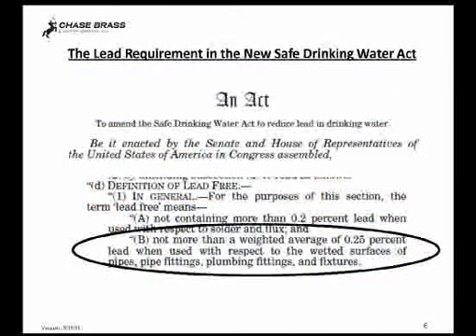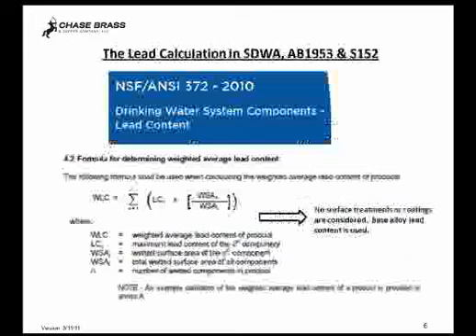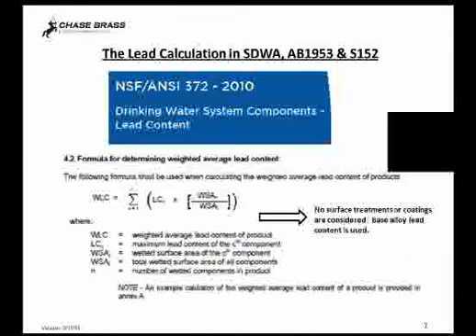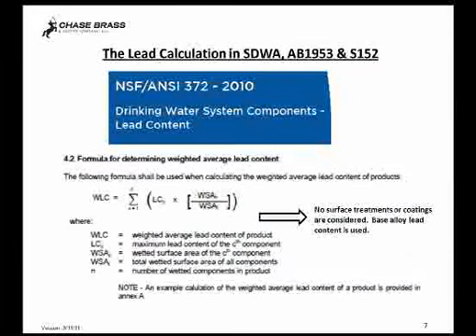The important part of the legislation that affects the products that we're talking about today is shown in the oval here. The term lead-free means that there's no more than a weighted average of 0.25% lead when used with respect to the wetted surfaces of pipes, pipe fittings, plumbing fittings, and fixtures. And what that means is shown in the NSF 372 that was developed in order to help explain first the California requirement for a quarter percent weighted average maximum, and now the national legislation.